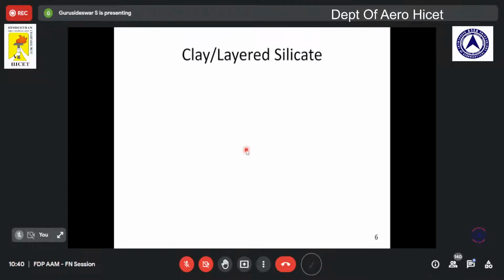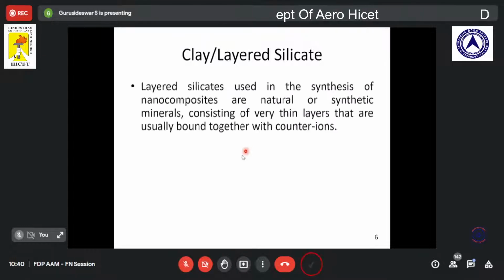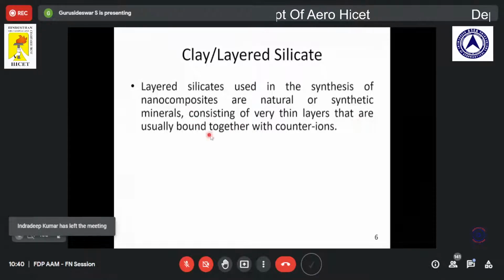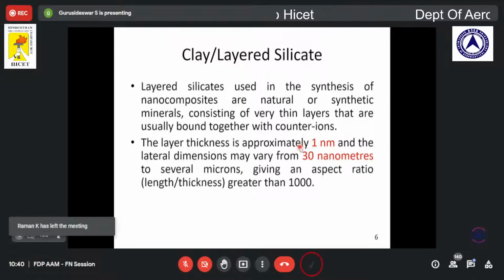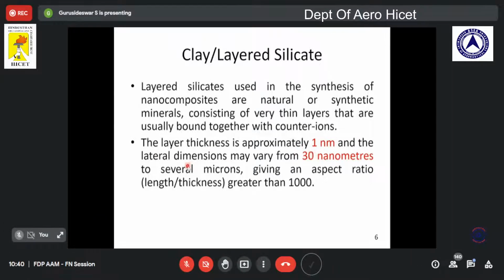In this work, we have chosen clay as the nanoparticle and an epoxy matrix as the matrix. So we are going to disperse the clay in the polymer matrix. That's why we say it's a polymer nanocomposite. Again, here we can see the definition of clay. It's a layered silicate, naturally available. It consists of very thin layers that are usually bound together with counter ions. As I told earlier in my previous slide, I gave the example of a nano layer. It has a layer thickness of 1 nanometer, and the lateral dimension may vary from 30 nanometers to several microns. Because of this, we have a very good aspect ratio.